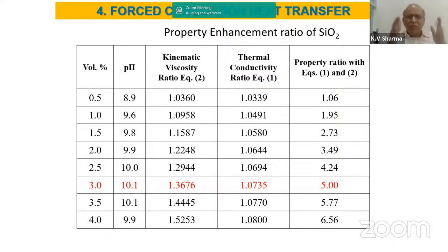Now, when I try to have the complete set of data in a tabular form, this is for SiO2. For SiO2, 3%, when we check the nanofluid pH value, whether it is acidic or basic, we see that it is in the basic range. Its kinematic viscosity is observed to be so much, thermal conductivity is so much. Then under turbulent flow, it has given a maximum at 5. That 5 we call the property enhancement ratio.